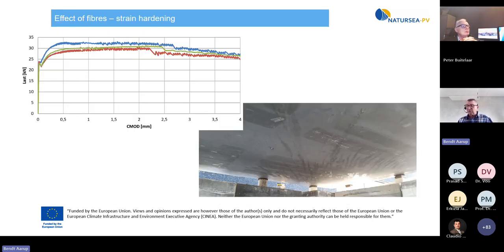We always use steel fibers with our mixes to ensure that we have strain hardening, to have good crack control. And the graph shown is from a standard test EN 14651 with some relatively large notched bars. But we want to make sure that we get multi-cracking performance, so we have a very ductile behavior for the concrete.